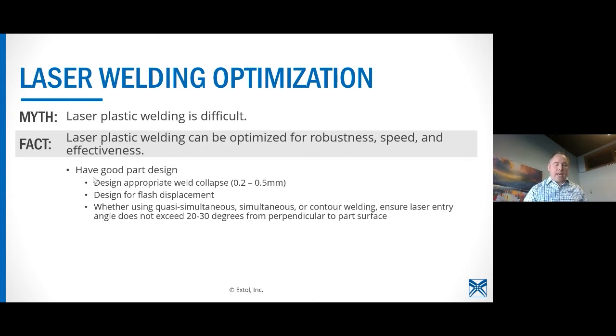And then sort of adjacent to that is make sure you're designing for flash. It is minimal. It is by far the least flash producing weld technology out there. And you'll see some photos of some examples here in a moment. As you saw in the video, the part, how thin that flash is. It's still important to consider. No welding technology is flash free, as we say. But what laser welding does do is it minimizes the flash less than any other welding technology, and reduces and most often eliminates particulate, which ultrasonic vibration can have.